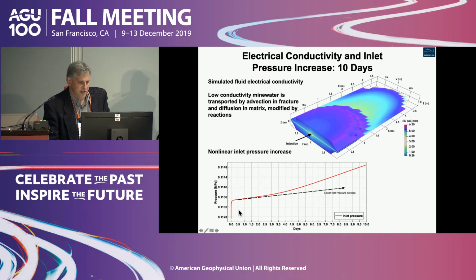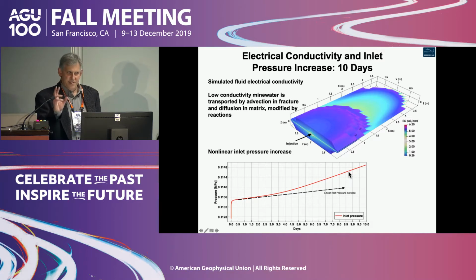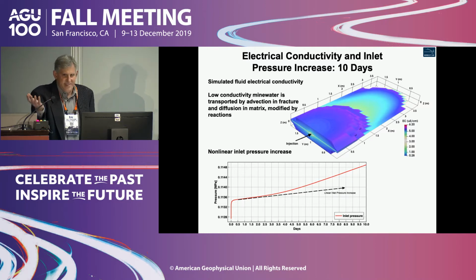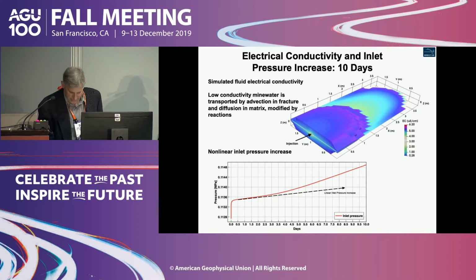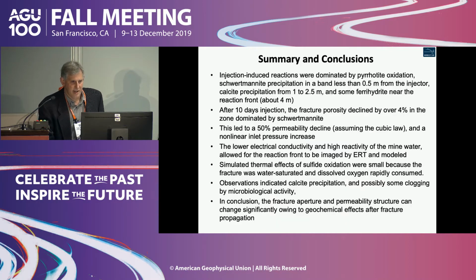And if you look at the pressure increase at the inlet, which is basically what you can measure in these sites, not a whole lot else at the inlet, the pressure will non-linearly just keep increasing because of this drop in permeability. A linear increase in pressure would just be like this. So this is probably a lot more than you would get through just the simple poroelastic effect, and it would keep continuing if we were to run this longer and longer. And it makes sense. I mean, these are the things you see in mines with oxygenated water.